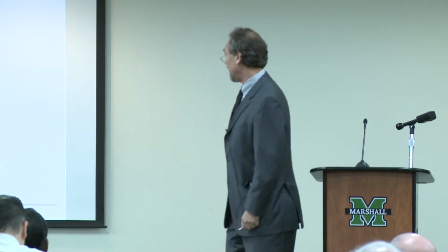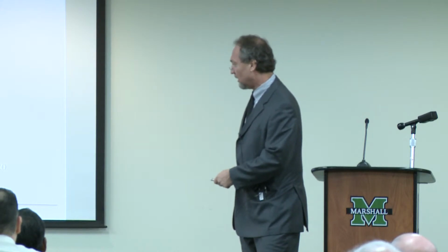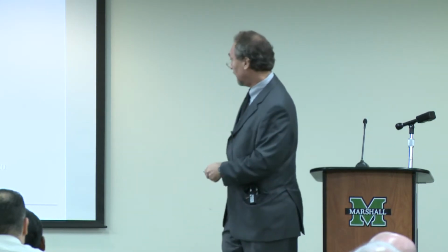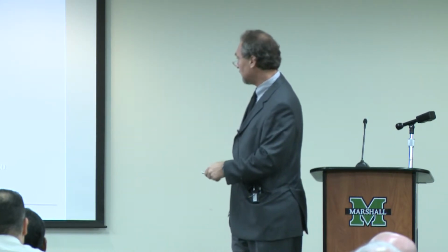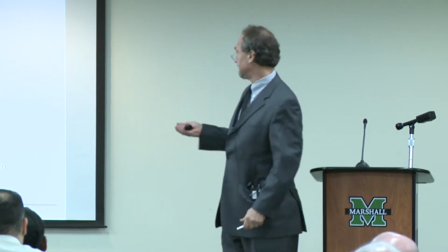Okay, now the bolometer needs to be characterized, so you need to know certain things about it, so you know if you see a signal what power is being detected. And I can skip over that, but this is the resistance versus temperature. This is only 1/10 of a Kelvin. So this bolometer's got a transition. It's pretty narrow. It's about 1/10 of a Kelvin. And the resistance is around 10 ohms, 10 to 0 ohms. The slope of that's called the sensitivity.